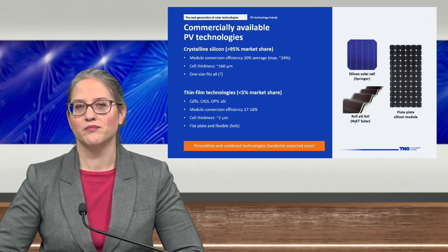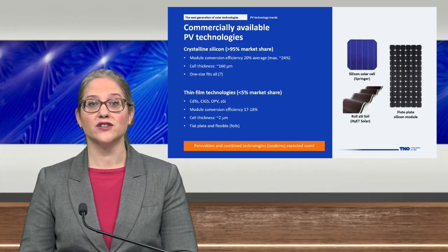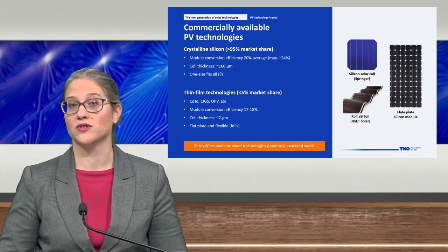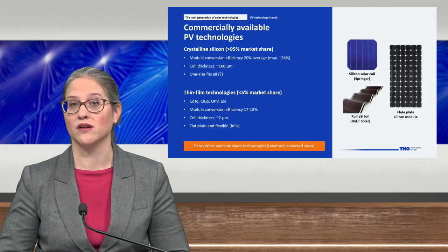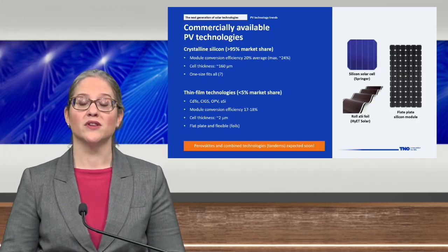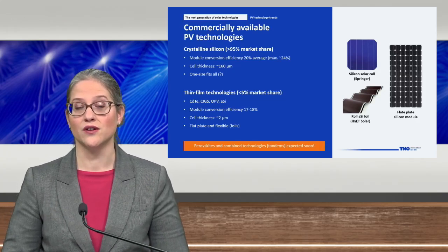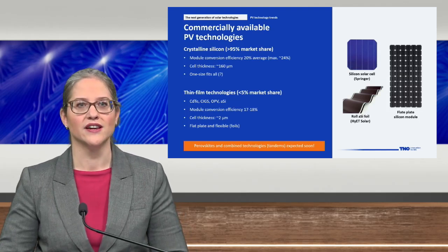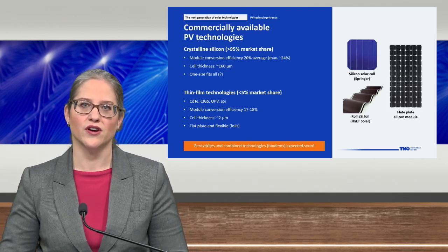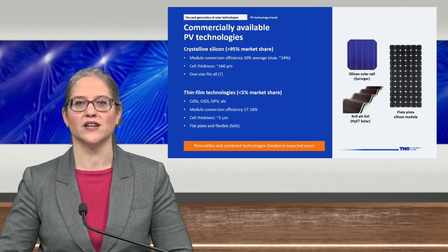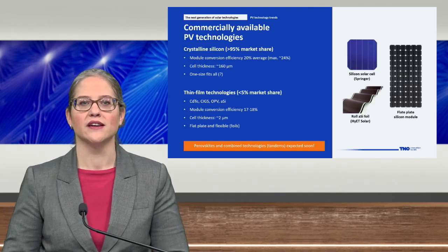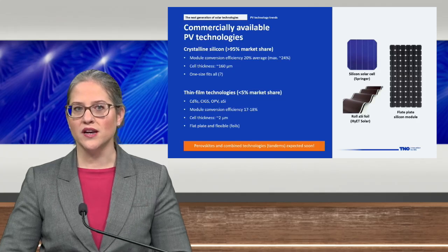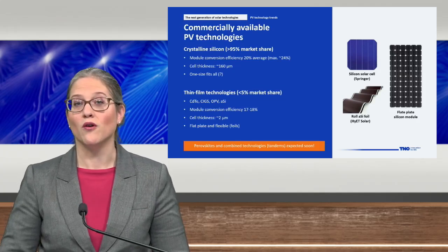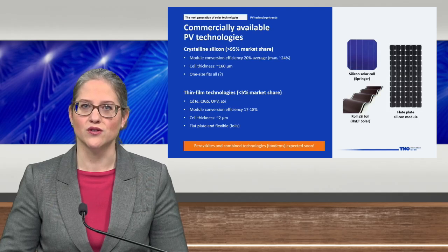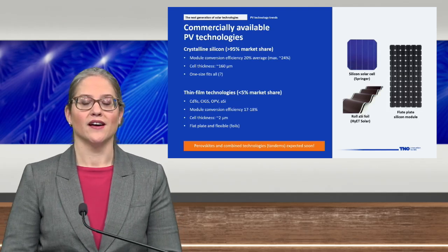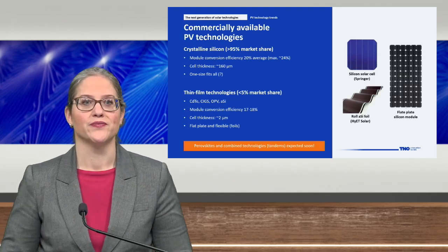These panels have conversion efficiencies of about 20% on average and can go up to about 24%. But the cell thickness of a crystalline silicon cell, due to its nature, needs to be above 100 micrometer. And the standard is about 160 micrometer. And the panels are typically one size fits all. Well, or maybe one size fits almost all, or maybe nobody anymore, when all the standard fields have been filled.